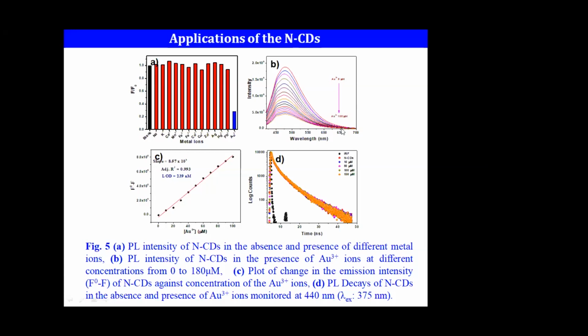Now you can also see that these materials are sensing metal ions. We can really see that it is able to sense, in the sense of fluorescence quenching of the intensity of carbon dots as you add the gold solution to this. This is how you could see the fluorescence intensity quenching, but the fluorescence lifetime remains the same, which clearly tells us it is not dynamic quenching, it's static quenching. One can evaluate the concentration region, the limit of detection. It's almost like one can detect gold on the order of 240 nanomolar level, so one can identify or estimate the concentration of gold using these carbon dots, and the sensing range was better too.